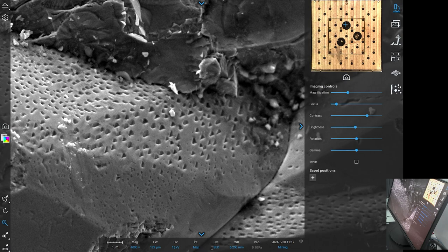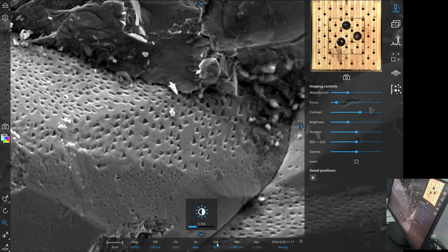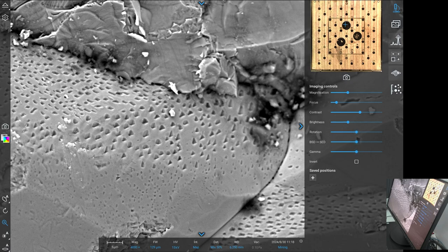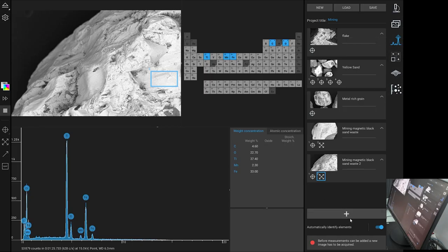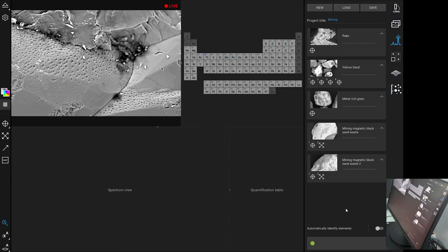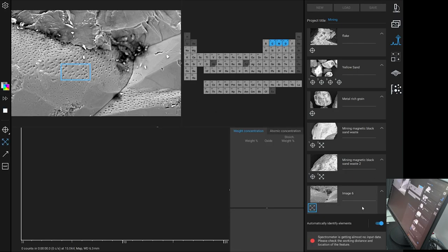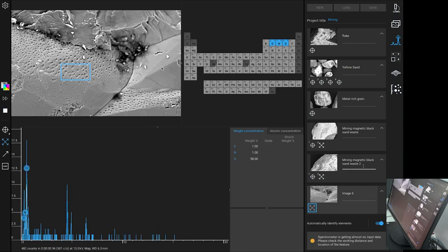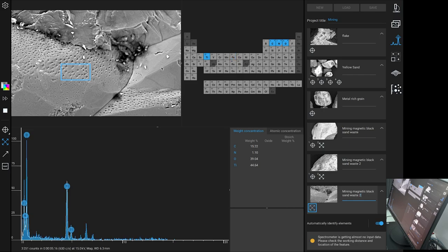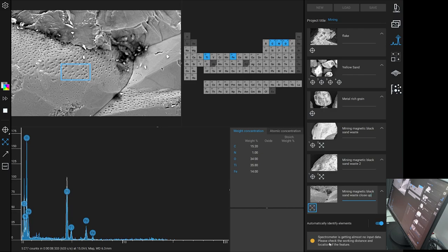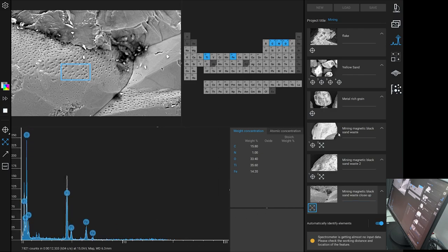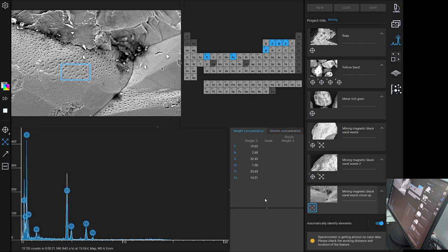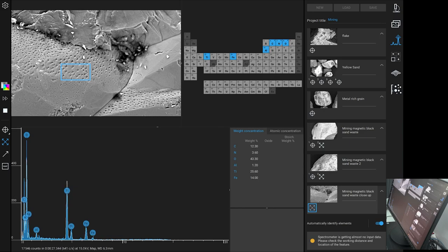Okay so I'm going to do a mix here so we can see the elements. Right and then we will go and do an element analysis here. And what we're seeing here is again high concentrations of iron and titanium oxygen. That's basically it. This phase looks more titanium rich and we'll have a look at this phase over here.